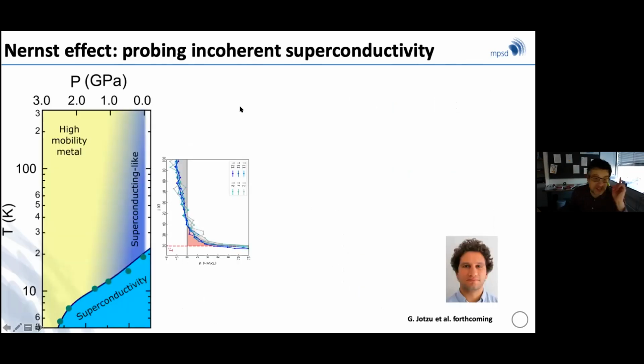And so the first statement that I want to make is that, if you want to draw conclusions, we seem to be seeing this light-induced effect in systems that exhibit a high temperature Nernst effect. That is the cuprates and some of the buckyballs. And so what we did from that, we said, well, maybe then any system that has a Nernst effect, if it's excited right, should also give rise to this light-induced transient effect.